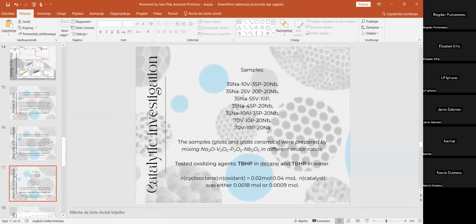For that reason, a set of samples was prepared, and they had different vanadium content, different alkali metal content, and different other transition metal content. For example, sodium ions were used as the alkali, and vanadium was used as the main transition metal oxide. In these glass and glass ceramics, there were also phosphorus atoms, so phosphorus oxide was used as a starting material, and the other transition metal added to this system was niobium, as a part of niobium oxide.